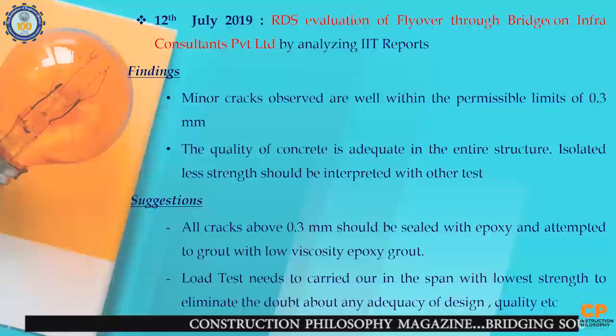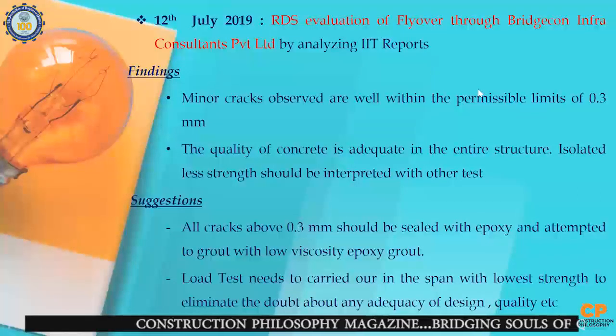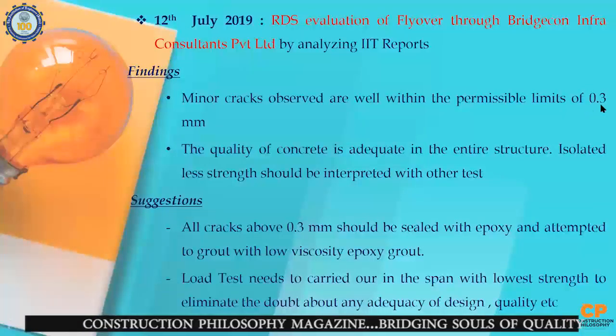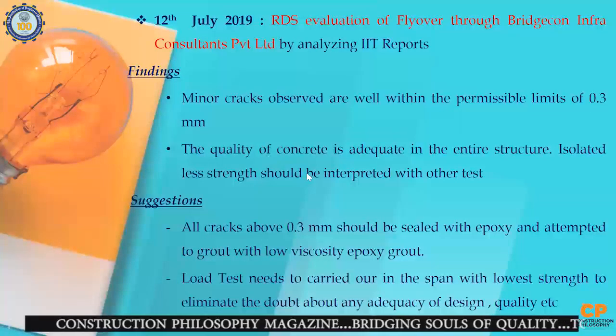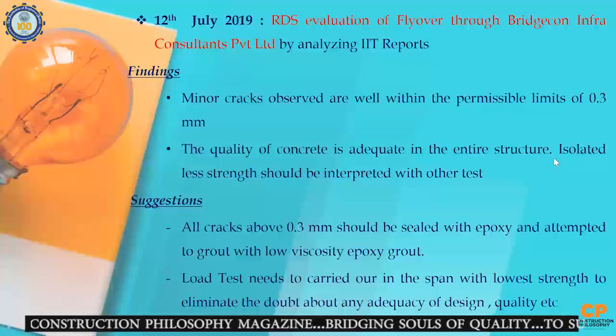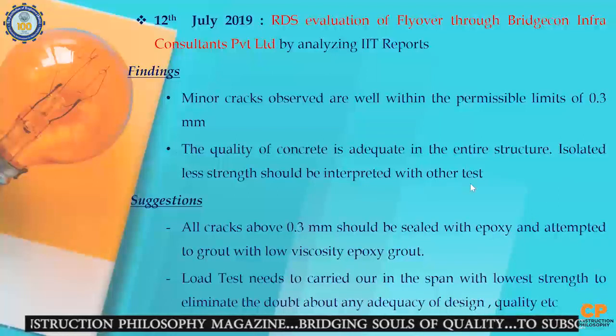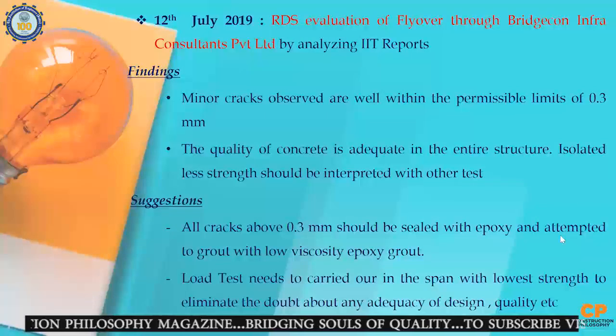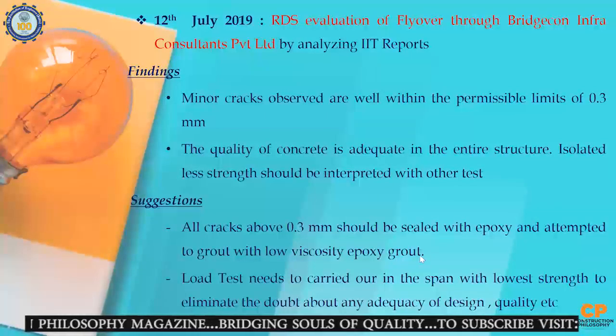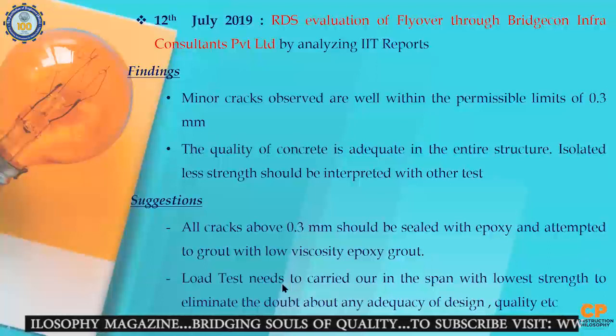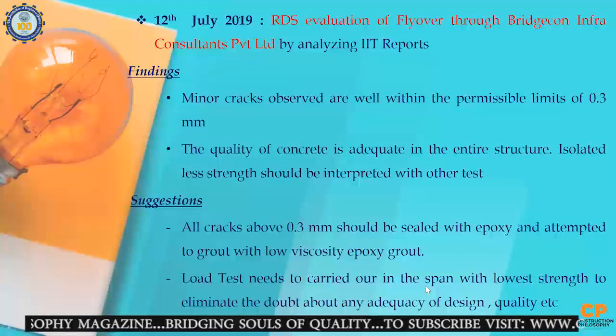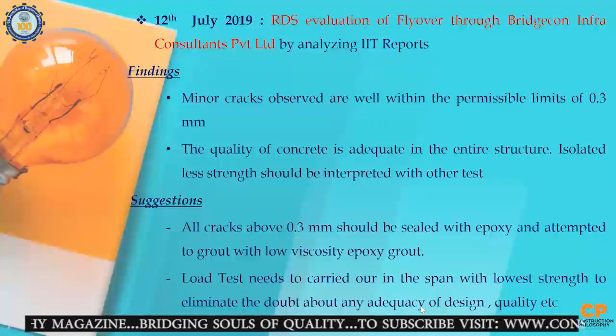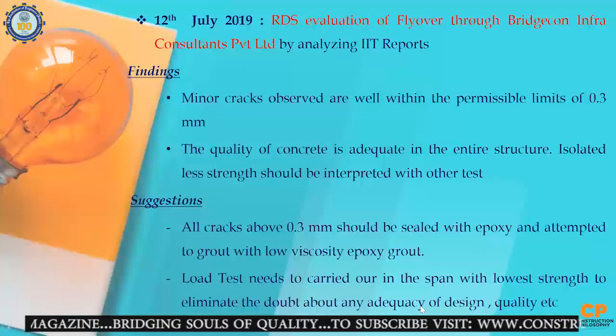And RDS's evaluation of the flyover through Bridgecon Infra Consultants was done by analyzing the IIT reports. The finding was that minor cracks are well within the permissible limit of 0.3 mm. The quality of concrete is adequate in the entire structure. Isolated low strength should be interpreted along with other tests. All cracks above 0.3 mm should be sealed with epoxy and attempted to be grouted with low viscosity epoxy grout. And load tests need to be carried out on the span with the lowest strength to eliminate any doubt about the adequacy of design, quality, etc.